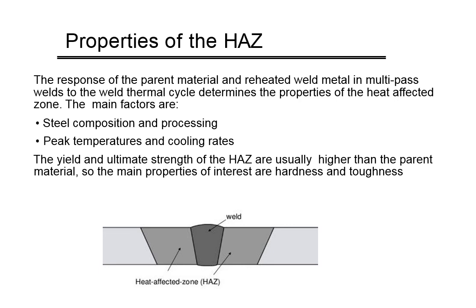So we really need to watch out and make sure we don't have a heat affected zone that's going to be harder, softer, or outside the boundaries of what our materials should look like. So we really need to keep an eye on the HAZ. A lot of times when you do a weld procedure qualification, they'll do a bunch of tests on the HAZ, hardnesses and whatnot, so that you have a good idea of what your weld's going to look like as far as hardness and ultimate tensile strength, as well as your HAZ, and then see how big your HAZ is going to be.